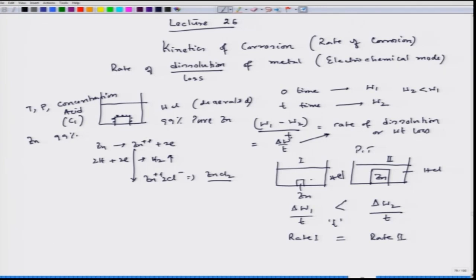So, but it is not like that, because you see this quantity and this quantity, they are different. Now where is the problem? The problem is, since we are considering that the surface reactions are taking place and the bulk of the system is not participating in the reactions, so we have to normalize with area. When we normalize with area, because only the area is taking part, and here it has got much higher area than this particular situation. So that is why the weight loss would also be higher, and when we divide it by the same time duration, this particular factor would become much higher.